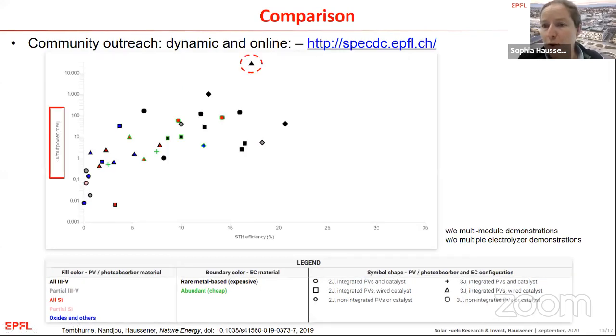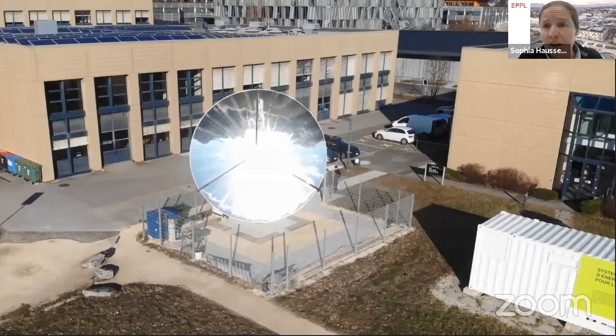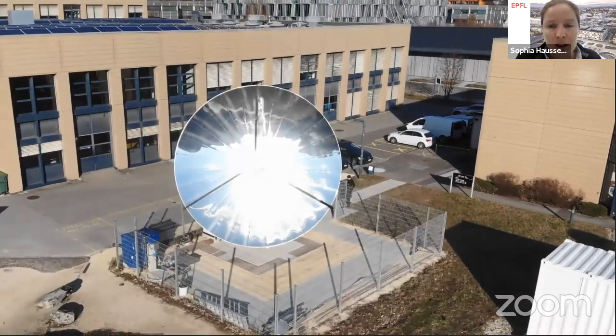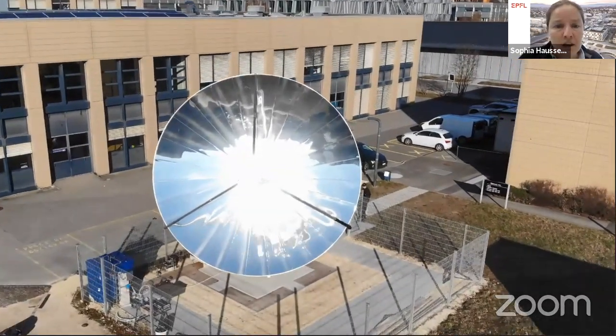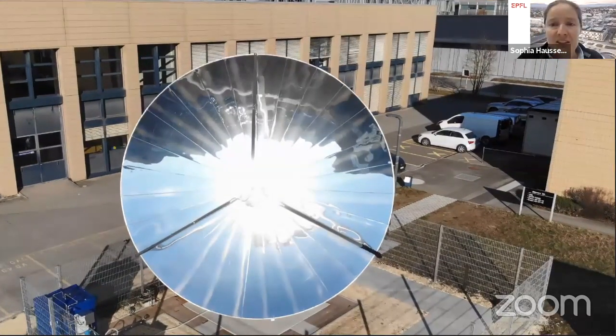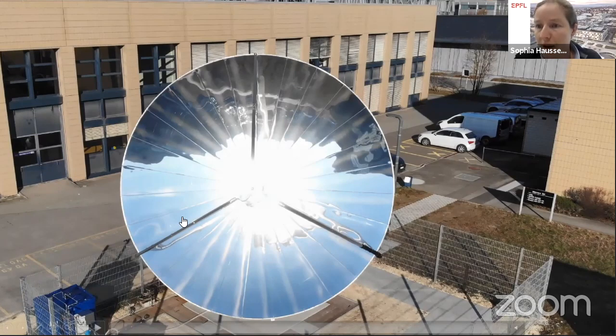So same demonstrations. Now I show on the x-axis the output power. And even though we have a 2 by 2 centimeter photoactive area, since we use concentrated radiation, this results in a larger power. So you don't achieve scaling by simply increasing the area. You can also achieve it by using concentrated radiation. And this gave us the motivation to scale. And here you can see a nice scaling picture, or let's say this is our solar parabolic concentrator, which we installed on campus. This activity has been ongoing now for almost 3 years.